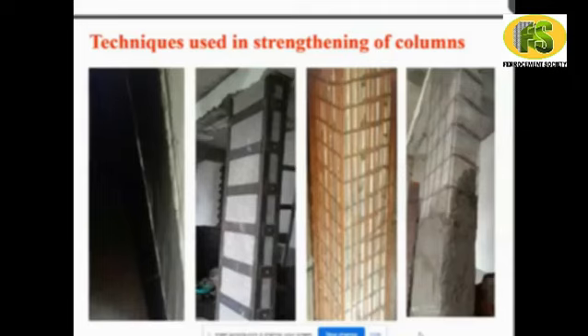For the beam also, we loaded the beam up to 60% of its strength. That means, for example, if the load carrying capacity of the beam is say 20 kilonewton, we applied only 60% of that, that is 12 kilonewton. And then after that, we wrapped this failed beam using the ferrocement technique, and then it was tested. Definitely these photographs are not with me, and that's why I am not in a position to show all these things. But we have done all these things.